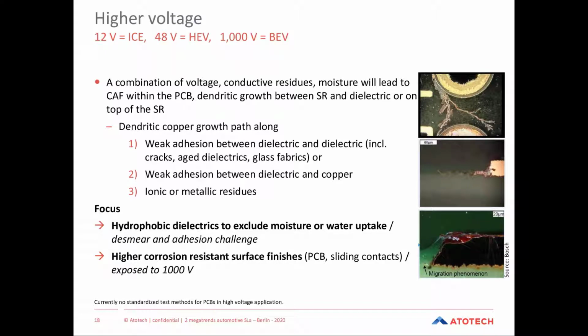On the right-hand side, we can see some images showing the dendritic copper growth. The top image shows copper dendrites growing on top of the solder resist. The image below shows dendrites on top of the dielectric underneath the solder resist, so it grows within the dielectrics. And the one on the bottom shows a dendrite which grows through the solder resist at the corner of the conductor where the solder resist is thinnest.